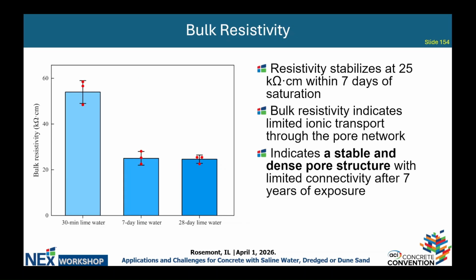And also for the bulk resistivity, we used the same curing conditions for the extracted cores up to 28 days. At the early age, it showed a drop in the bulk resistivity due to the degree of saturation. However, after 7 days, it showed a constant value up to 28 days, around 25 kilo ohm centimeter, which can be classified as a high resistivity to chloride ingress. And this can indirectly indicate the excellent durability of this system.